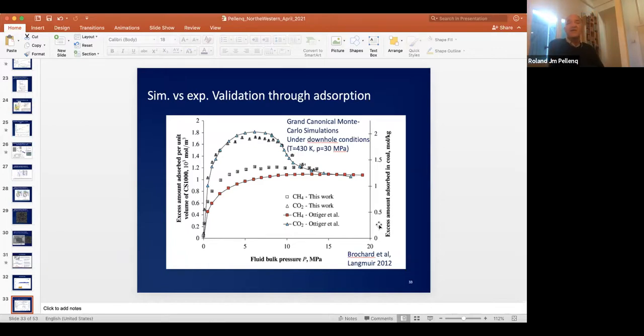And then we can compare to experiments, and we see that the comparison is pretty close actually. For CO2 and for methane, we can predict the adsorption isotherm with no issue. And there is not even a need for this kind of reactive potential in this case, because this is physisorption, so there is no need to describe chemistry. So a simple Lennard-Jones function will work for doing that.